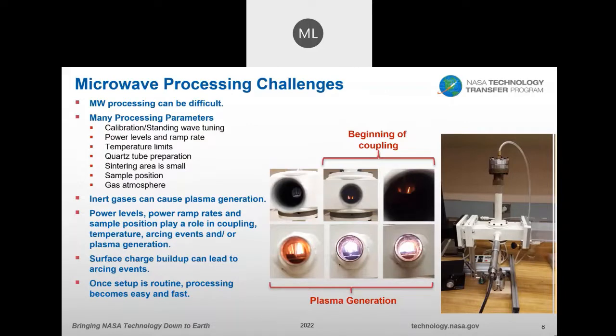So before I get into what we did, we also have to consider that there's a lot of processing challenges with the microwave. However, once you've overcome a lot of these challenges, the process can become quite routine. But some of those challenges would be like calibration of the standing wave, tuning the microwave once you have your material inside the furnace, temperature limits, preparing the quartz tube, sintering area is small. In our particular research furnace, there are manufacturing furnaces where some of these things can be overcome.